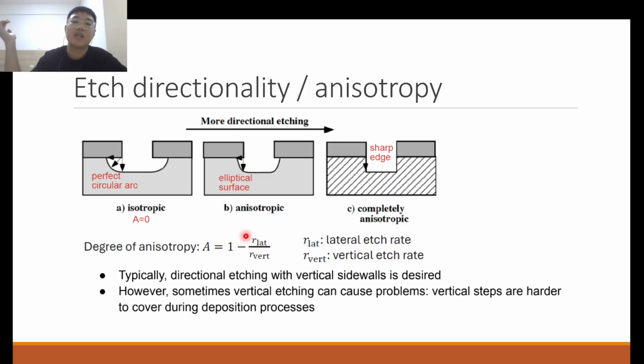However, if your lateral etch rate is the same as your vertical etch rate, that means it cannot distinguish between left, right, and down. It is the same in all directions. Then this fraction over here will be 1, and 1 minus 1 will give you 0. So it's not anisotropic at all. It's perfectly isotropic.